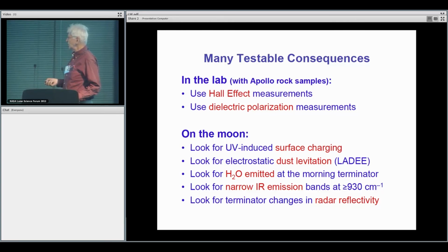Look for narrow infrared emission that we have shown to exist when these charge carriers recombine. There is a very characteristic infrared emission around 9.7 micron and longer wavelengths. And then maybe even we have seen changes in radar reflectivity that result from the activation of these electronic charge carriers that are characteristic of the oxygen valence minus 1. So the next slide just is the end. And thank you. I just wanted to solicit a lot of questions, because this is an interesting and potentially quite important aspect that should be taken into consideration. Thank you.